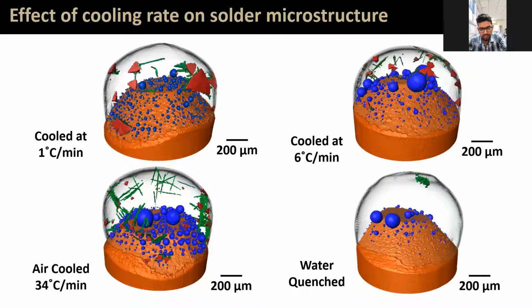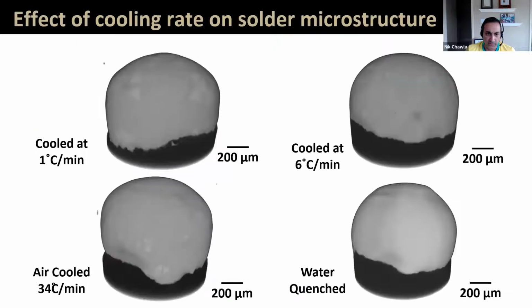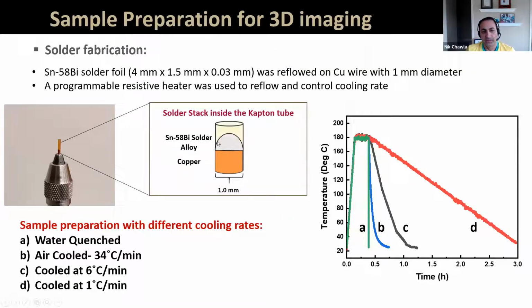What are the specifications of samples, like liquid sample or thin film? Can we measure it through it? Yeah, you can do. So this actually starts off as a liquid. You start with the solid, we heat it up, it becomes a liquid. We typically use this kind of Kapton tube because it's X-ray transparent. So in this case, we want to be able to contain the liquid as it's solidifying. But you can do these experiments in a corrosive environment. We've done experiments in 3.5 weight% sodium chloride, which is essentially seawater.